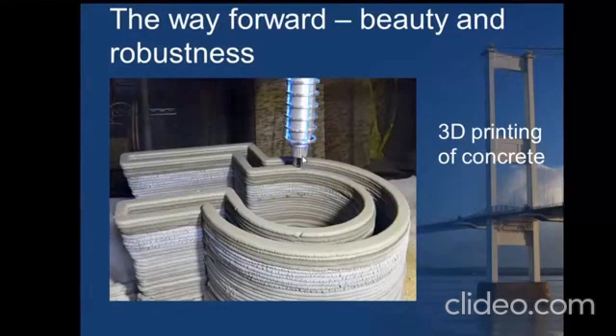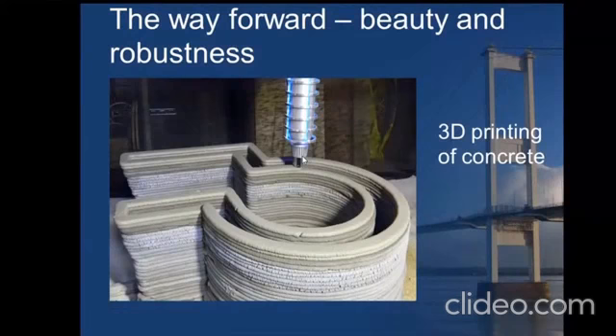And one thing I missed out in the lightweight aggregate concrete was that we were talking about aerated, I think foam concrete. When I told you fly ash can be used or fine sand can be used, the same thing applies with aerated concrete also. You cannot use fine aggregate greater than 300 microns in aerated concrete. Either you need to pulverize the sand or you need a very fine particle size distribution of fine sand in aerated concrete. So that is one important aspect.